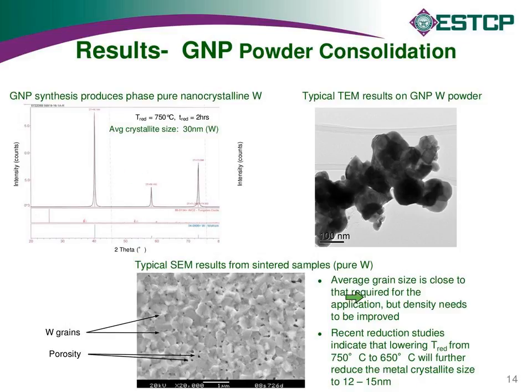And the microstructure down at the bottom is an example of one of those early sintering trials. Again, not full density, so there's a fair amount of residual porosity in this sample, but we had pretty good grain size. It looked promising at this point, with a sub-micron finished grain size in the material.